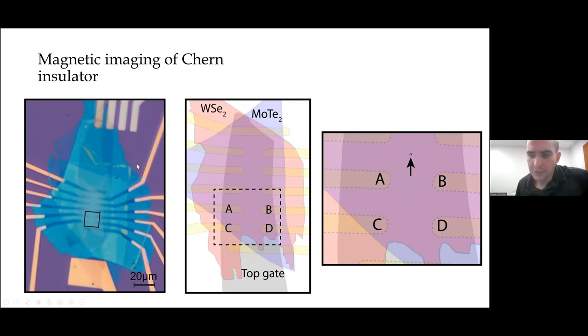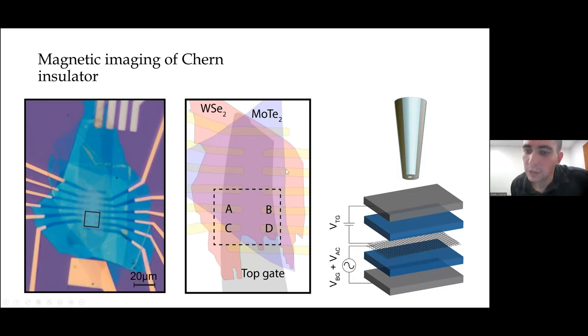So the next thing that we can do is use this nanoSQUID tool to image the magnetic order. So what we're doing is we're applying an AC voltage to the bottom gate. We're keeping a DC voltage on the top gate, and we're measuring the AC magnetic field associated with the excitation applied to the bottom gate. So that gives us something like the derivative of magnetic field as a function of bottom gate.